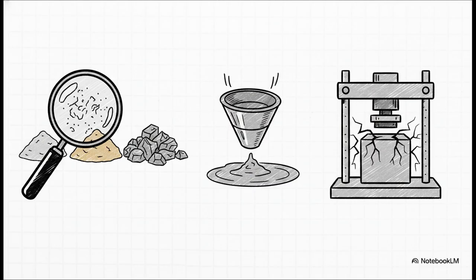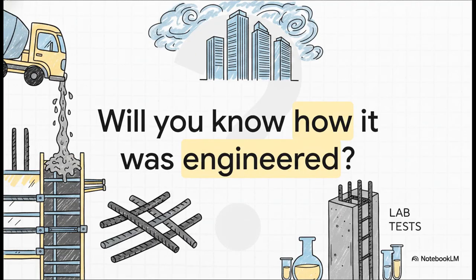After that, for those concrete cubes we cast earlier, we cure them in water for up to 28 days. Then they go into a hydraulic compression testing machine. That machine applies a slow, gradual load until the concrete cube systematically cracks and fails, which lets us calculate its exact ultimate compressive strength. With a design mix, your required strength is completely justified by hard data and rigorous lab tests. No assumptions allowed.